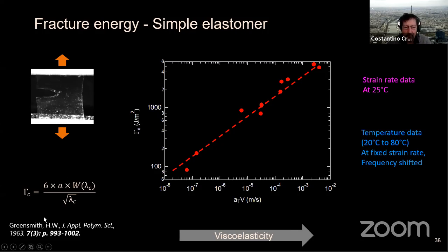So we are using the approximation of Greensmith. We take the integral under the stress-strain curve up to the fracture point. A very simple way to get the fracture energy. Certainly, you could use a better one.